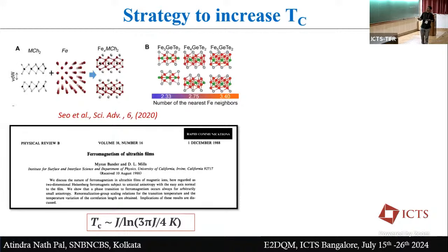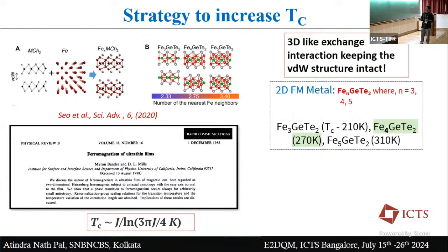Okay. So the idea is how you can increase the TC in the case of a 2D van der Waals crystal. One of the ideas is that you take a metal chalcogenide type of van der Waals structure and you incorporate iron inside this structure, keeping the van der Waals system intact. In that way you can get a structure like FexMCh2, where you can already see that iron is embedded in this system. There are of course several possibilities, but only 3 structures could actually be stabilized, and these have been observed in FGT-type systems: Fe3GeTe2, Fe4GeTe2, and Fe5GeTe2.